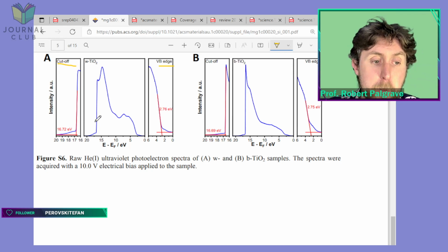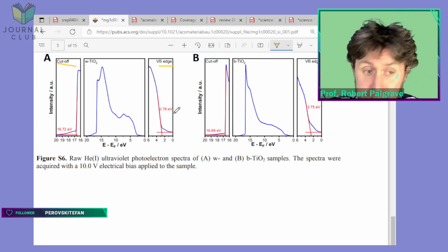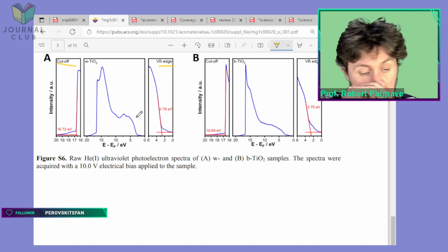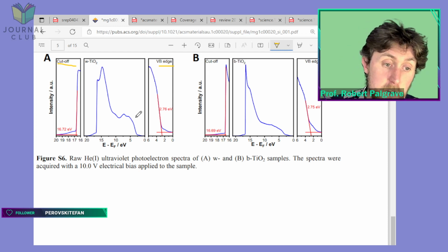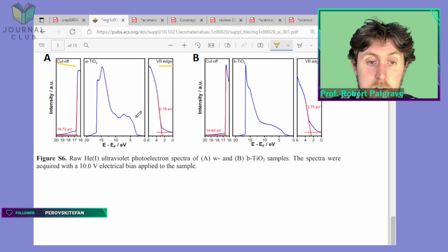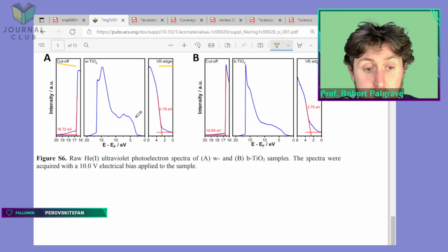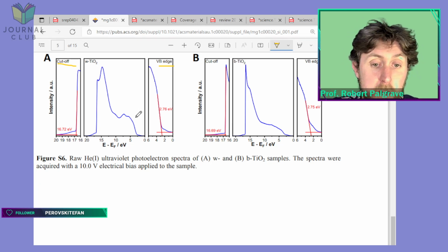By measuring these two cutoffs and the difference between them, and comparing that to the photon energy which they use, which they know, it's 21.1 electron volts, they're able to work out the work function. So this is a nice way to measure directly the work function of a surface.